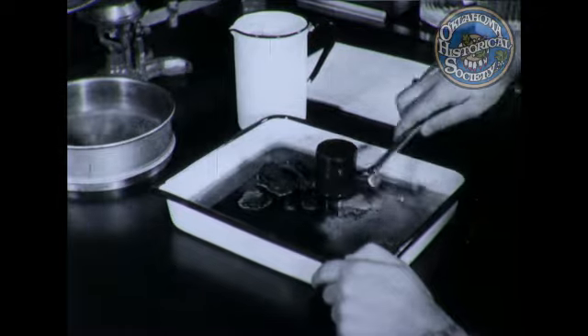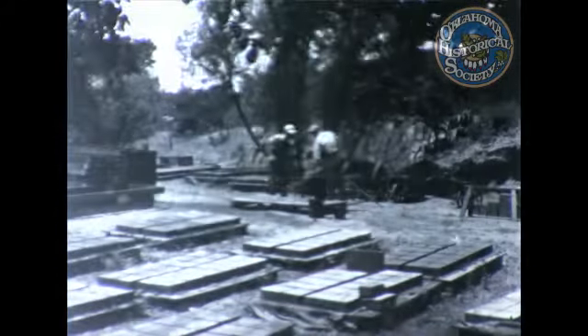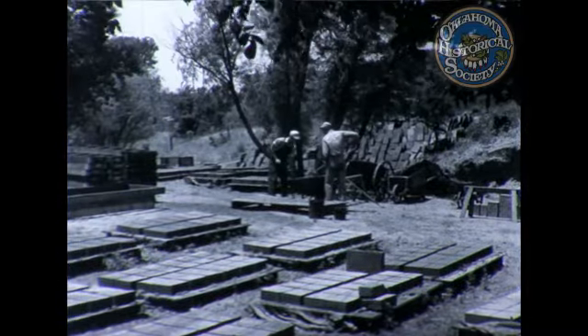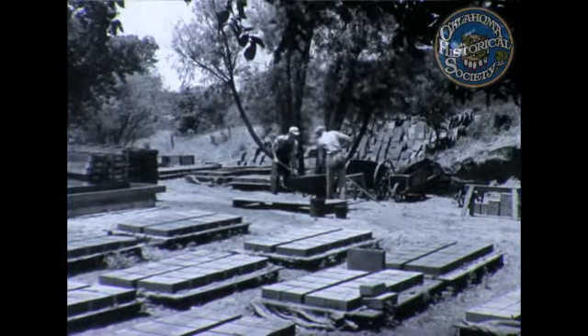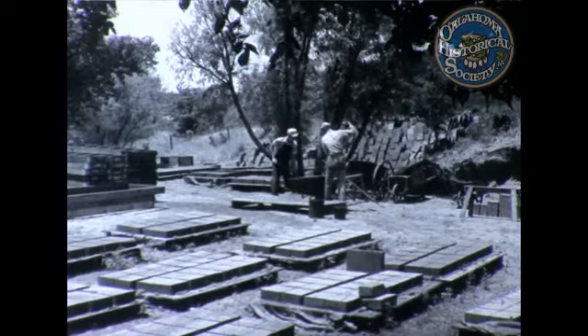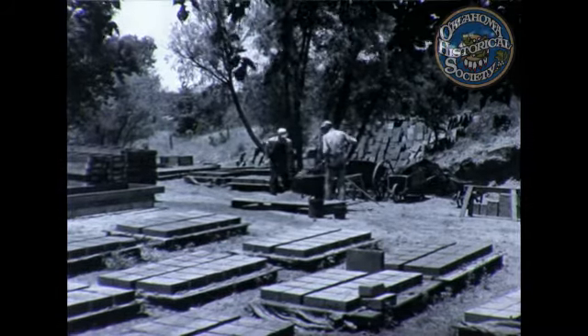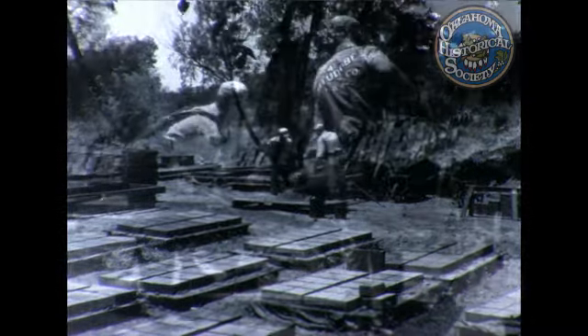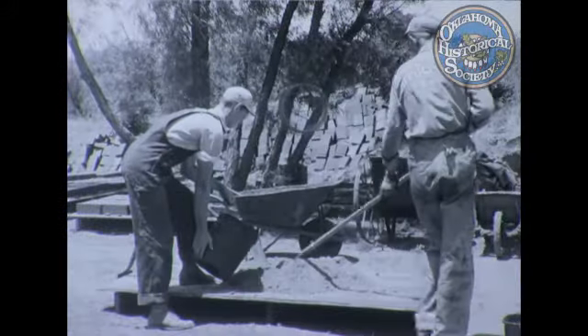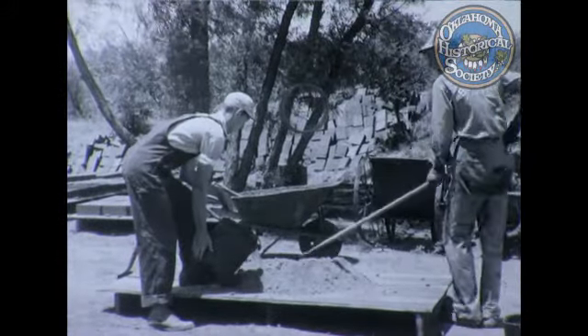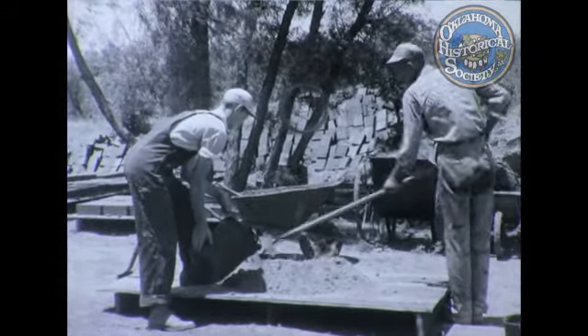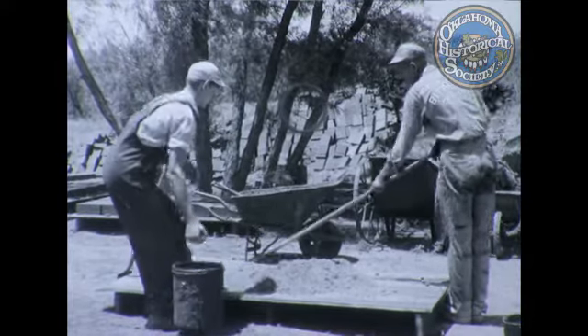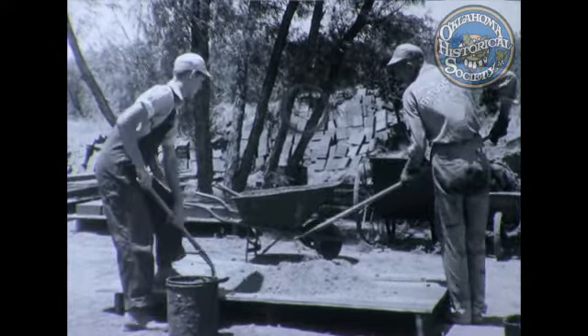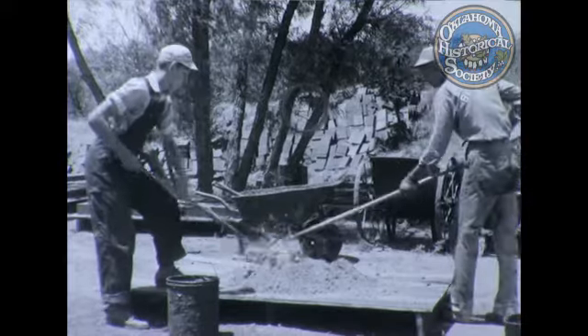Actually, when the engineer collects his data, he subjects these treated samples to at least 7 days of water absorption and makes many measurements of stability and percent water absorption immediately after the 7-day exposure to water. Here we have 2 men taking small portions of the soil, mixing them with water and emulsion on an ordinary mortar board.